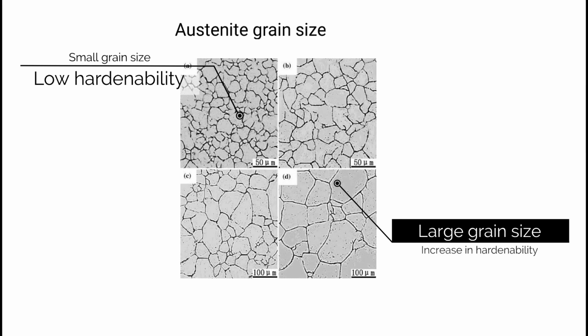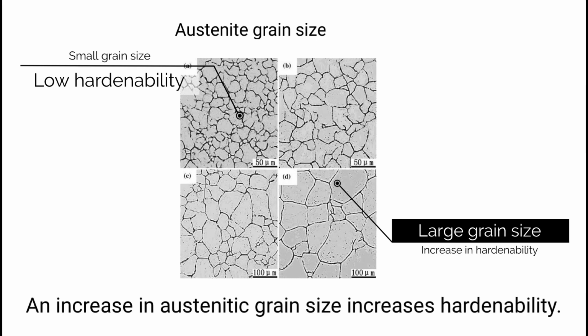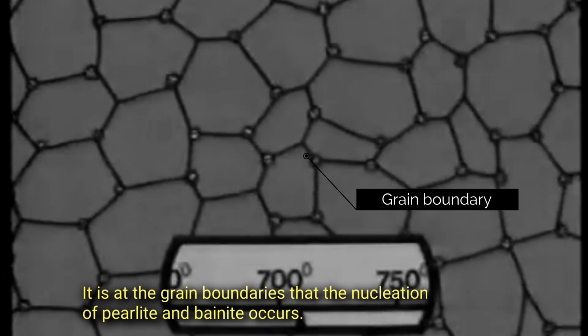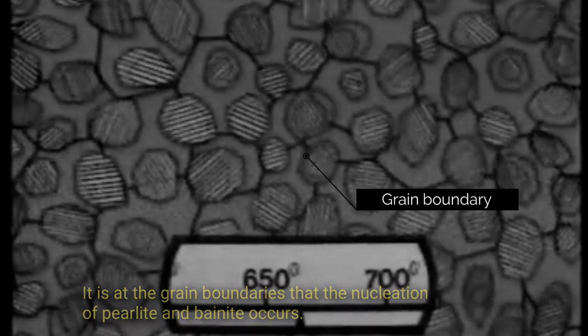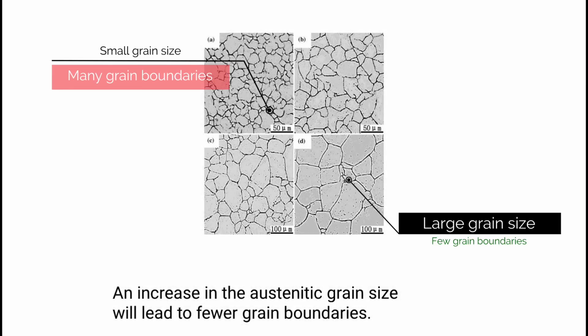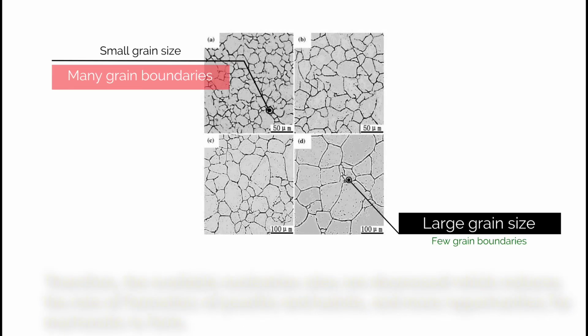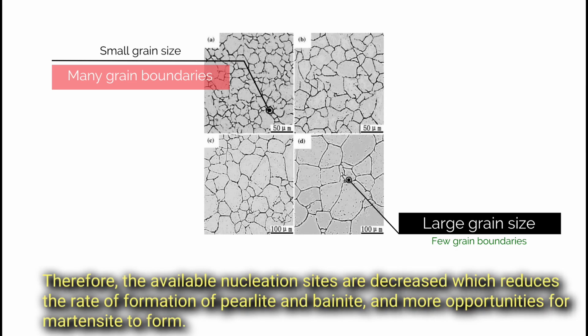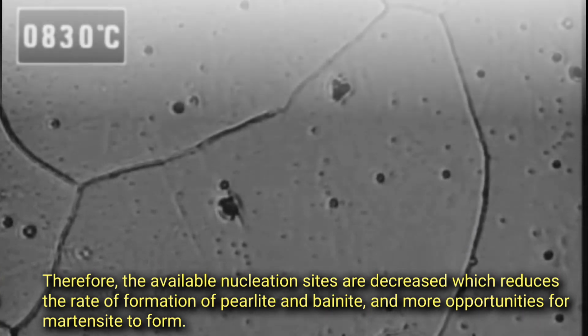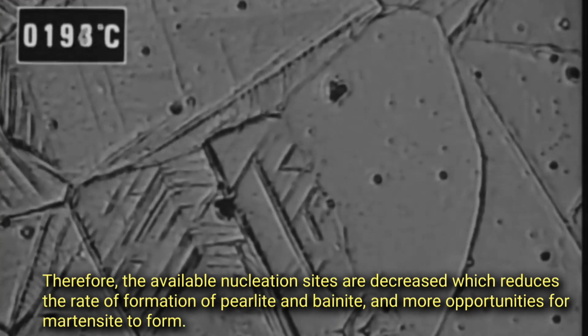Austenite grain size. An increase in austenitic grain size increases hardenability. It is at the grain boundaries that the nucleation of pearlite and bainite occurs. An increase in the austenitic grain size will lead to fewer grain boundaries. Therefore, the available nucleation sites are decreased, which reduces the rate of formation of pearlite and bainite, and gives more opportunities for martensite to form.